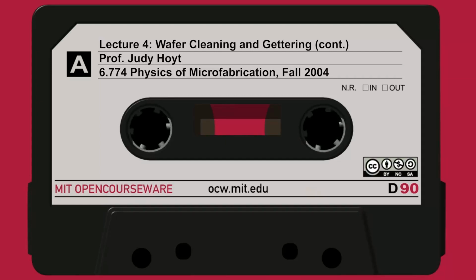So let's go on to slide 14, which talks about metal gettering a little bit more. And this plot on the vertical axis is temperature, and the horizontal axis is atoms per cubic centimeter. It represents the solubilities of the fast diffusing metal as a function of temperature. So if you look at any point on this curve, if you have a concentration higher than that at that temperature, then the metal will tend to precipitate out, will not be in solution.